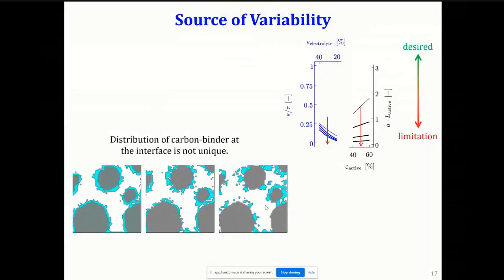Another method was doping your carbon binder with iron. The issue that came out was the contrast. You cannot detect the contrast. If you dope it with iron, it's a high Z material, and then you would be able to get the contrast to detect it. So there are ways around it. Now, the question is that you're changing your system in each of these techniques. So is what you're imaging really what you want to image, or are you imaging something else just because you went around it, right? Those are really the open questions for the entire field right now.